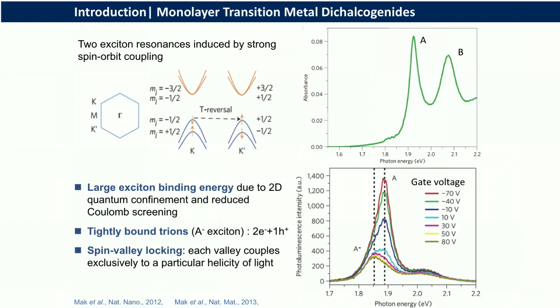And what happens here is, because of this different spin splitting, if you shine right circularly polarized light, then you can excite only one valley, although energy-wise they are degenerate valleys. So you only excite one. And with left circularly polarized light, because of the conservation of angular momentum, you excite only the other one of the two valleys. So by doing this, spin-selective optical excitation, you can address one valley or the other. And this has basically led to this excitement of what is called valleytronics.